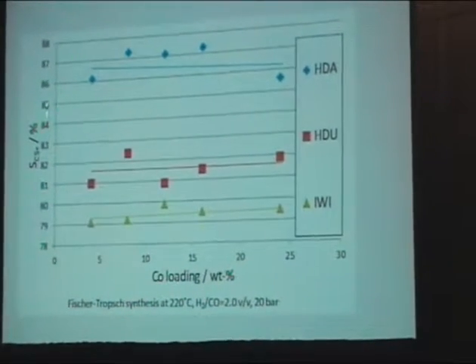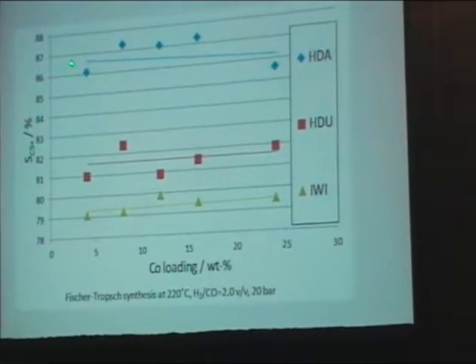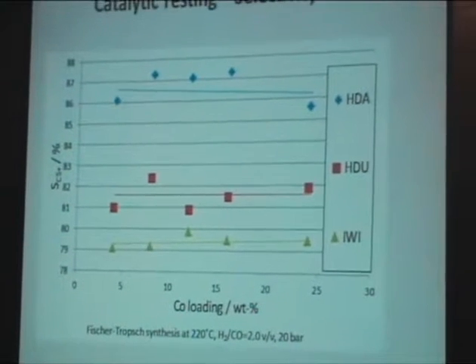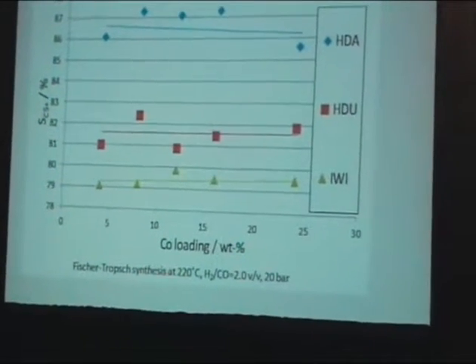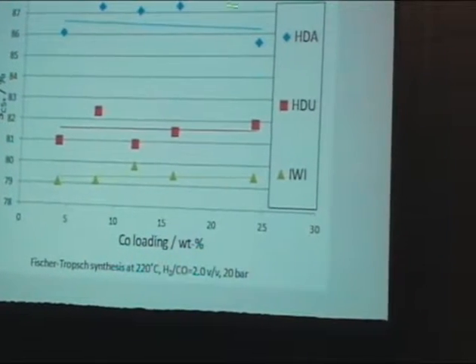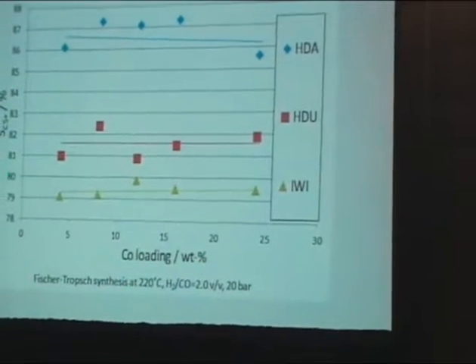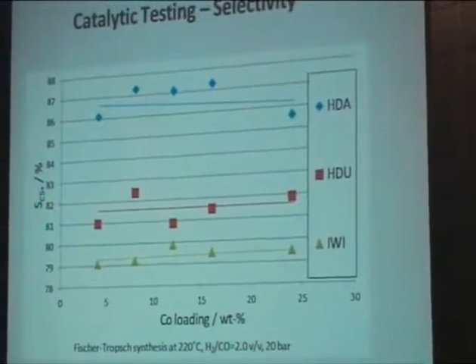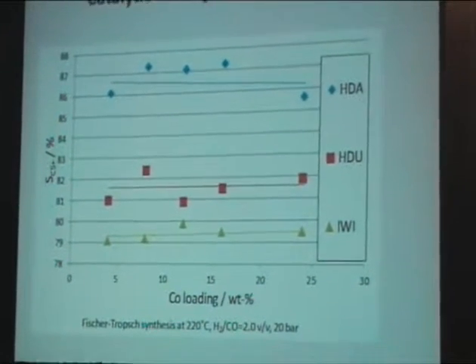Surprisingly, the C5 plus selectivity, and this should be in weight percent, consistently is significantly higher for the HDA catalyst. Partly because of a conversion effect, but the conversion effect is much smaller than this very significant effect that we measure for this series of catalysts. So this is for us now a topic of study. What's going on? It's cobalt and titania, no promoter. There are dispersion differences, but higher dispersions usually give you lower C5 plus selectivity, also studied by the Holmen group in the past. And I think it's not straightforward to assign this to a dispersion. So it may be distribution, it may be something, the activation of the titania. That's something that we are currently studying.